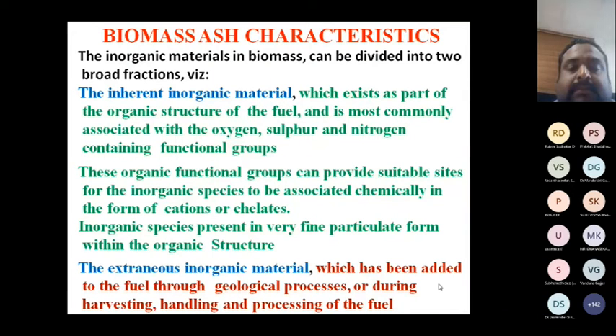The inorganic materials in biomass can be divided into two broad categories. One is inherent inorganic material, which exists as part of the organic structure of the fuel and is most commonly associated with the functional groups of oxygen, sulfur, nitrogen. Something like, in chemistry, you can understand COONa, COOK (potassium), or amine, NH2, with something attached to the amine. So these are all inherent inorganic materials. These organic functional groups can provide suitable sites for the inorganic species to be associated chemically in the form of cations or chelates. So these inorganic species are present in very fine particulate form within the organic structure.